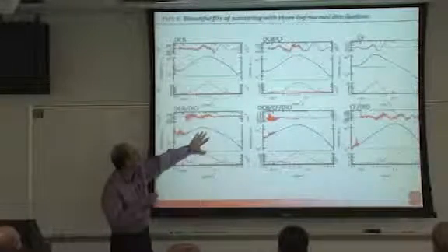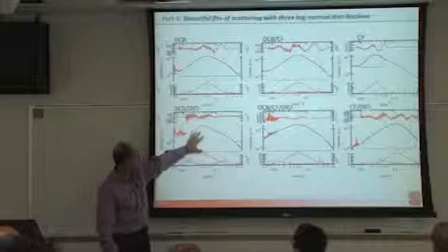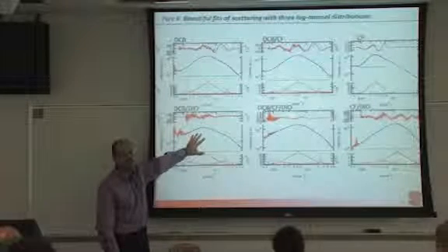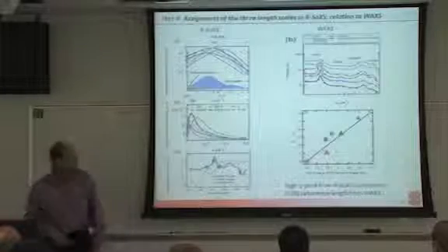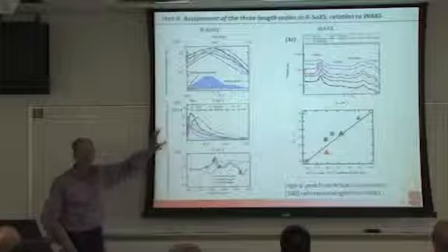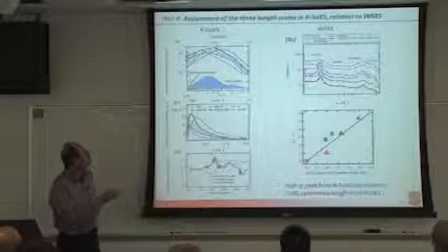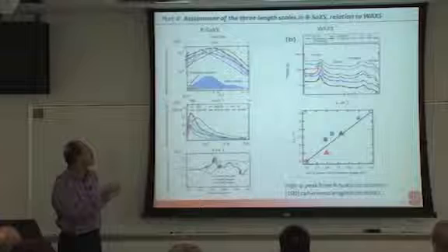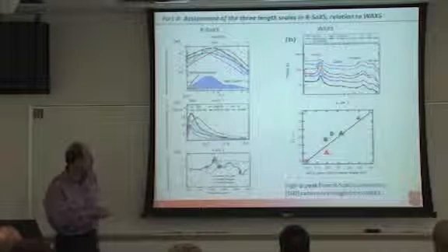So this is a material cast from different solvents. We get extremely good fits with 3 log normals. We can understand them from the energy dependence, that the lowest Q peak is the thickness or roughness fluctuations. The other ones are composition fluctuations. So this is clearly a hierarchical system.